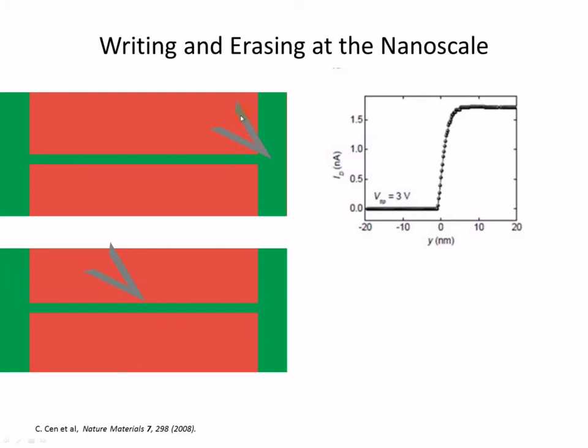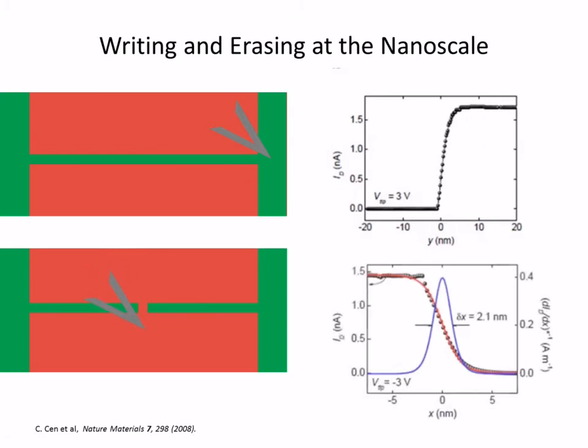And the idea is that we may be able to undo the writing process that we've created. So when we do that, we can also monitor the conductance, and we find that it goes back down to this insulating state. So we are able to reverse it. But what was really surprising to us when we did these experiments was the sharpness with which it went from the conducting state to the insulating state. And in a sense, it provides a measure of the width of this wire.